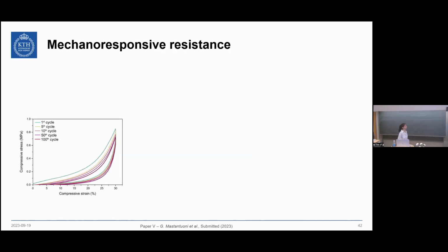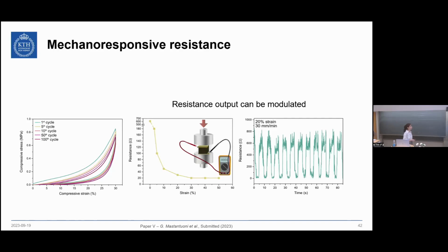Furthermore, this material presents very interesting mechanical properties, meaning that it is compressible in the radial direction. These are 100 cycles of compression of the material, and we can see that there is not a lot of loss in strength even after 100 cycles. Furthermore, as this material is conductive, because we introduced PEDOT:PSS, if we connect the material to a multimeter and press it at the same time, there is a reduction in the resistance output from the material, the more we compress it.